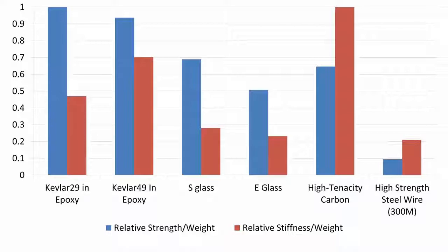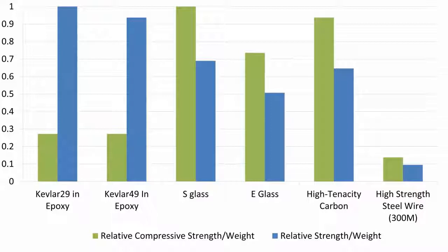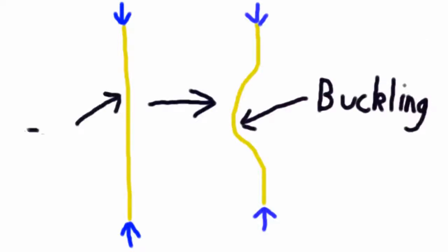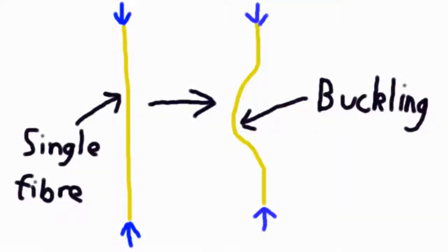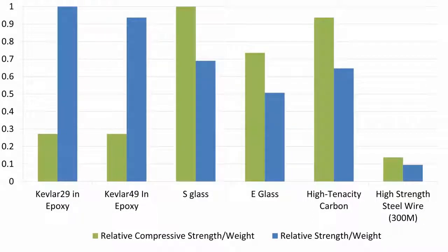The interesting thing with Kevlar, now I was talking about how strong it is, but if we are to reverse the direction of our loading and put the material in compression, all the other materials do quite well. But if you have a look at this graph, you'll see that Kevlar loses a considerable amount of strength when you load it in compression. Now, what happens is you get a micro buckling of the fibers. Basically, you press on the ends and they flex out. And so Kevlar has almost no strength in compression. In fact, usually the fibers buckle before the matrix, which is quite an interesting phenomenon.